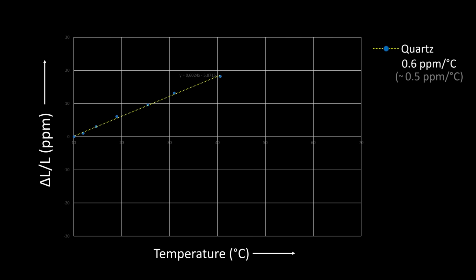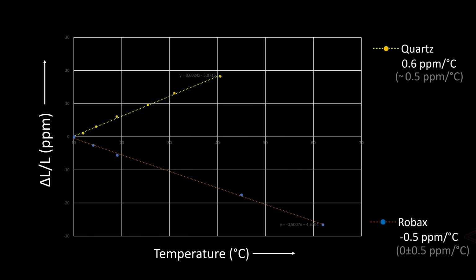We'll take the values of quartz as a reference because they are the lowest values from the previous graph and plot them on a somewhat different y-axis scale. Let me now show you the results for Robax. Turns out to have a value of minus 0.5 ppm per degree Celsius, a value that is still within the specified range of the datasheet. So this sample actually shrinks a bit when heated.